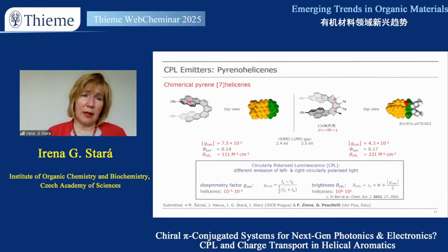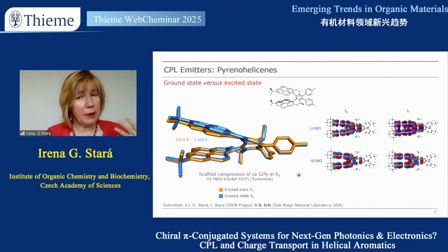These compounds, as you can see here, have a very good geometry for possible formation of a so-called internal excimer. The question was whether such high values of g_lum are really caused by formation of this excimer. To address this question, in collaboration with Stephan Irle from Oak Ridge National Laboratory, we ran calculations and confirmed that in this particular case, it is just the compression which is visible. Here the excited state and ground state are different in color: the ground state is depicted in blue, whereas the excited state is in yellow. If we compare these two, there is about 12% compression in the excited state.